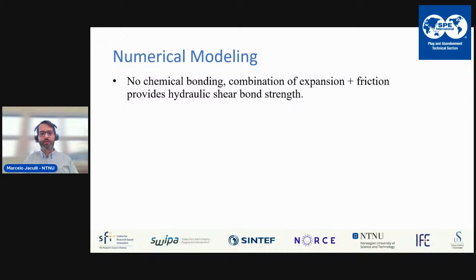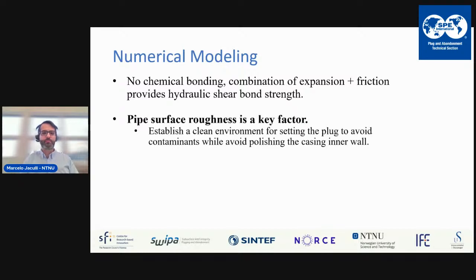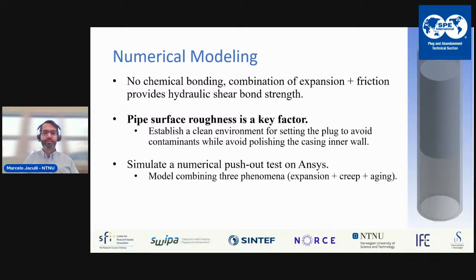So again, there is no chemical bonding. It's a combination of the expansion plus friction between plug and pipe, providing the strength against hydraulic pressure. We know that surface roughness is a key factor for this, so establishing a clean environment for setting the plug is very important, but also not polishing the casing inner wall too much. We take this to perform numerical push-out tests on ANSYS.